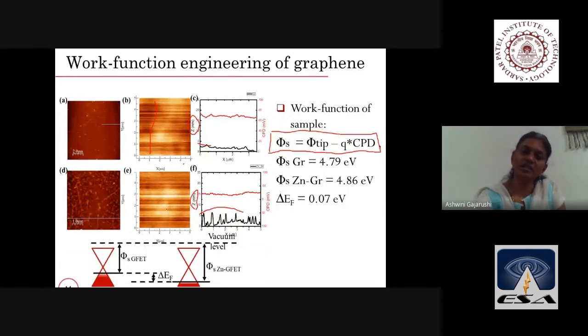And now the contact potential difference has changed to plus. This was minus 62, 63 millivolt or 65 millivolt. Now it is around plus 25 millivolt. And because of that, the work function increased to 4.86 electron volt, and the change in the Fermi level was found to be 0.07 electron volt. So this is the tool with which we can detect the work function of graphene.